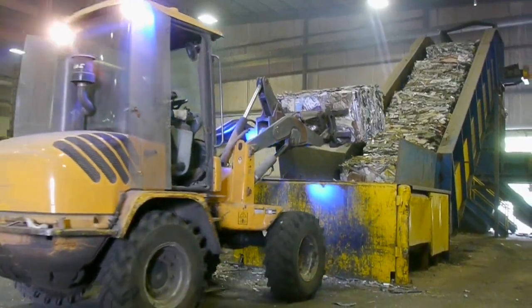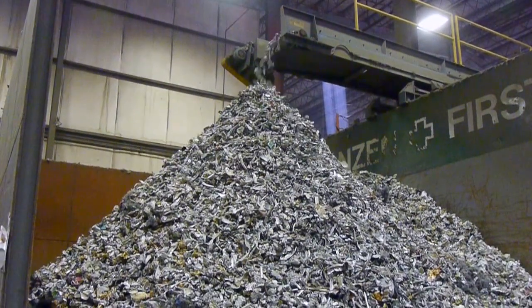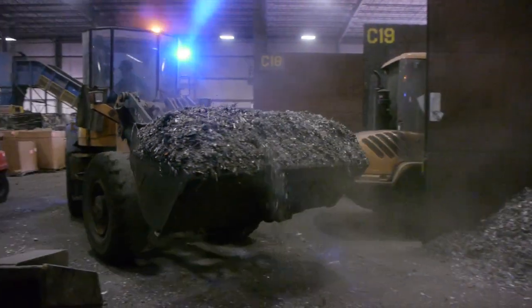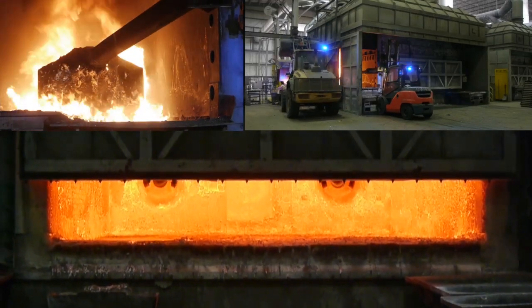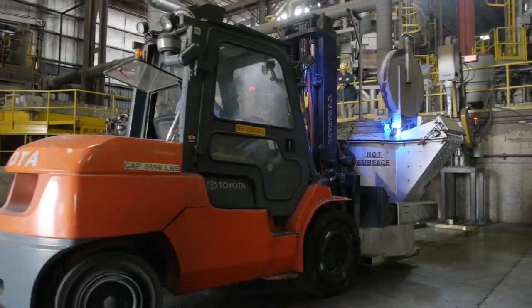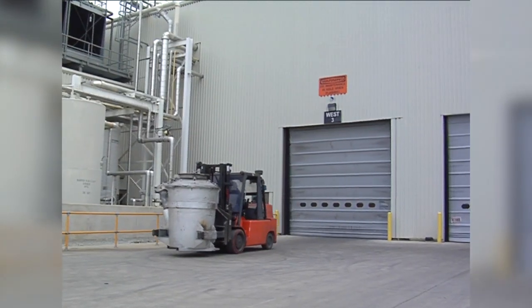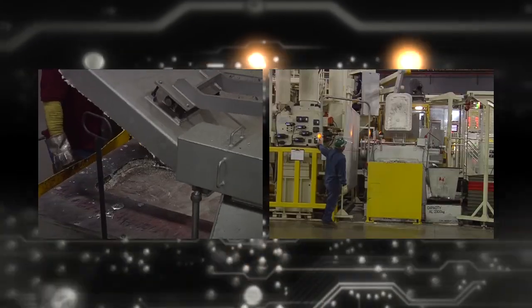Their process begins with taking recycled aluminum and crushing it to separate foreign materials from the aluminum. Once it has been separated, the good aluminum is mixed with silicon and other raw materials to create the specific alloy needed for our engine blocks. These materials are all melted together in a large furnace. The molten metal then flows from the furnace and is poured into large ladles. The metal in the ladles is then treated using argon gas to remove air and impurities. After this critical quality process, they deliver the molten aluminum to each one of our die-cast machines' holding furnaces.